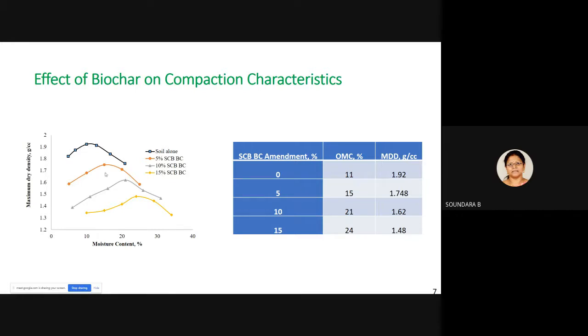Upon increasing the biochar, since it's a porous material, it could take up more water, so the OMC could be readily higher compared to the soil alone, around 15, 21, 24 for different percentages of biochar. And the MDD is reducing because the biochar is a porous material with a lesser unit weight compared to soil, so it is decreasing.